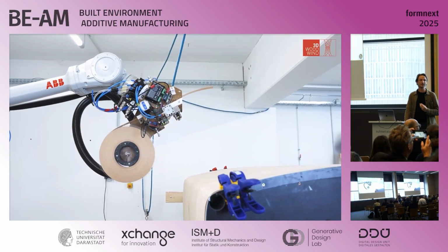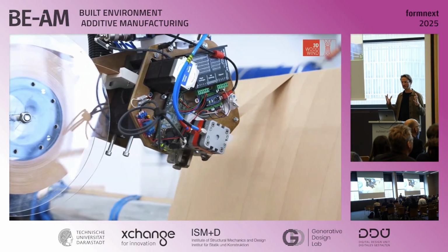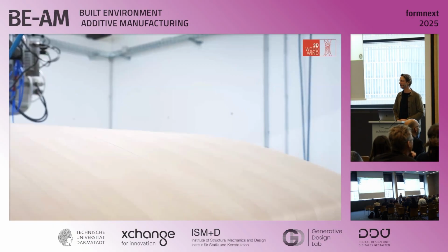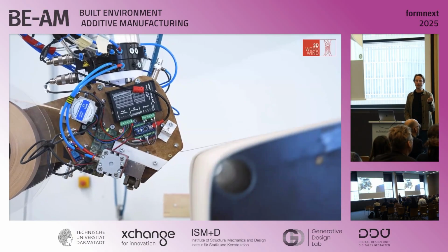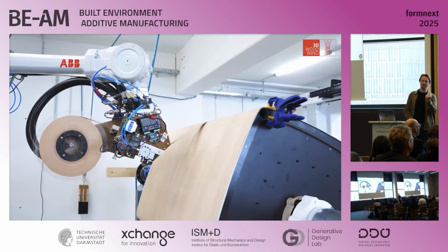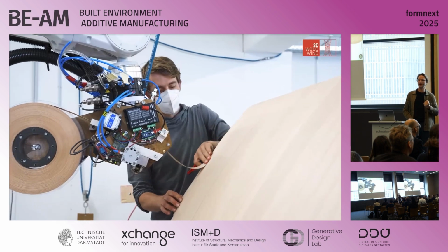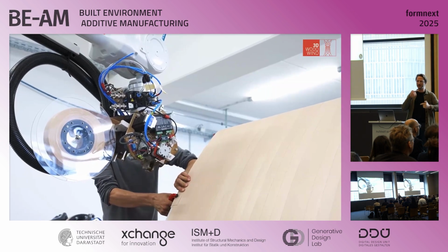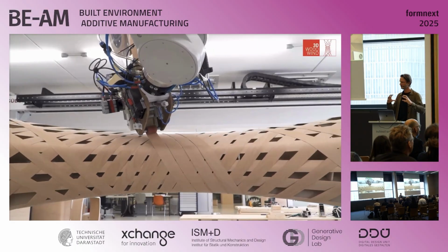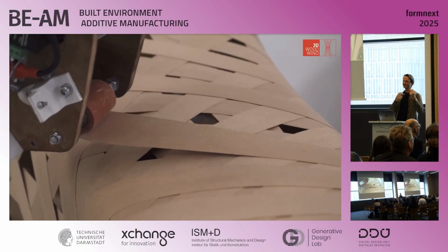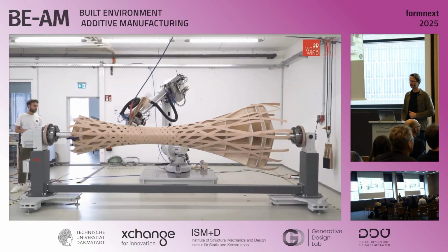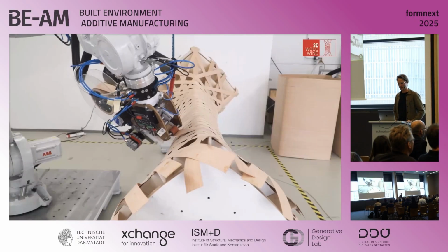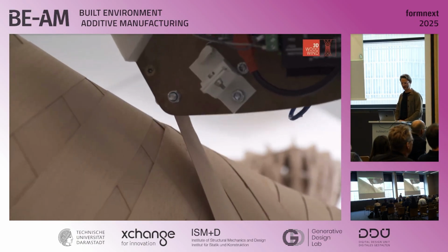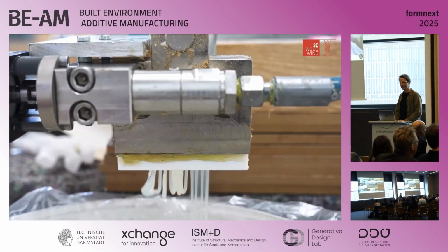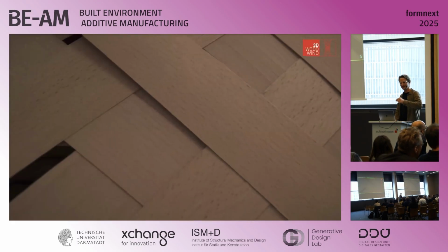Usually, for these types of adhesives, you have to later press, hot press, to cure the adhesives. What we are doing is different: during the process, we apply tension with a robot. So using the robot force, we really tear it on the mold, so it's a lot of tension on it. And this is enough that the tension goes into compression, and then it's enough to cure the adhesives. So this approach is, of course, much more efficient. See here a bit of testing, and the application of the adhesives in the process.